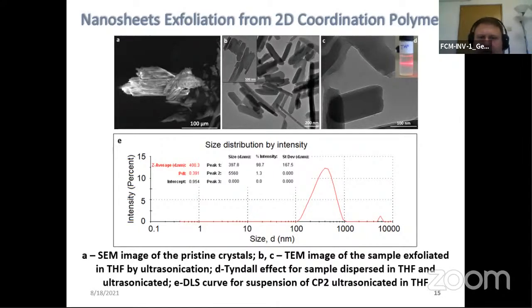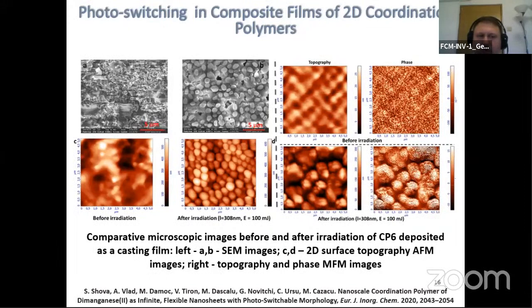Similar to the inorganic two-dimensional materials, coordination polymers such as these can be exfoliated into nanosheets by simple ultrasonication in different solvents, usually low to medium polarity solvents such as tetrahydrofuran. Also, an interesting capability of these polymers is that they present photoswitching. In the presence of a flash of UV light, they can self-organize into micron-sized formations, as seen here in atomic force microscopy images.